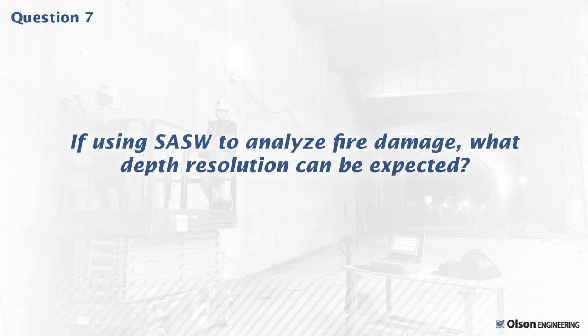Q: If using SASW to analyze fire damage, what depth resolution can be expected? Fairly good — with modeling you can actually determine depth of the lower modulus zone. Dennis thinks about half an inch resolution. We've done a number of fire damage studies. You always test an area of similar identical concrete not exposed to fire so you know how good 'good' is. Impact echo is also used as a complement. You'll need modeling if you really want to see the depth of the lower modulus zone.